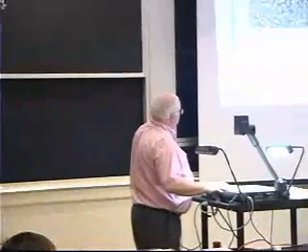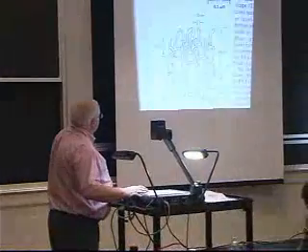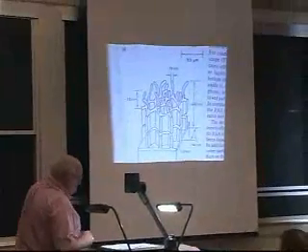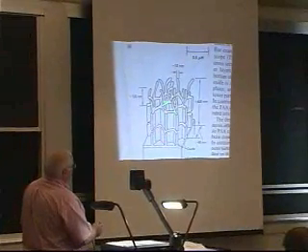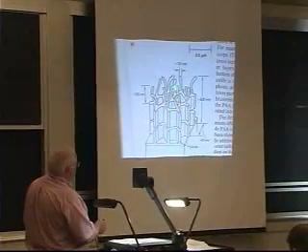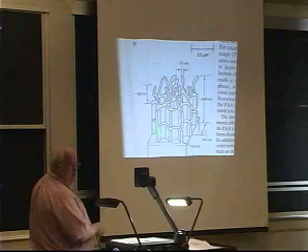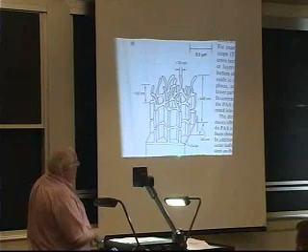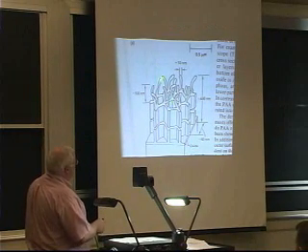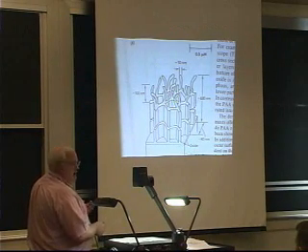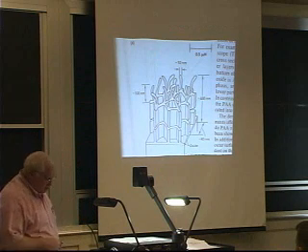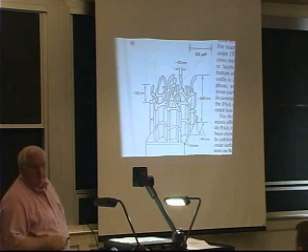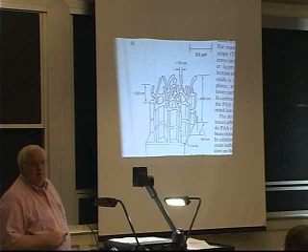People have looked, and this is a model of the aluminum oxide surface, where you grow these cells of aluminum oxide. You have these channels in between where the electrons are flowing through this liquid electrolyte. And when you're all done, you end up with, on a microscopic scale, a very rough surface, which is great for mechanical interlocking. Now, it's not so good for corrosion.